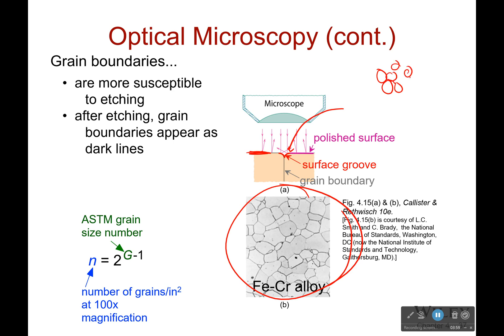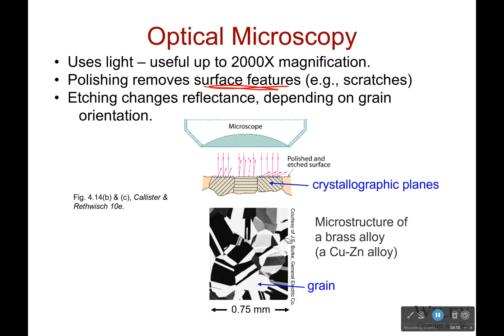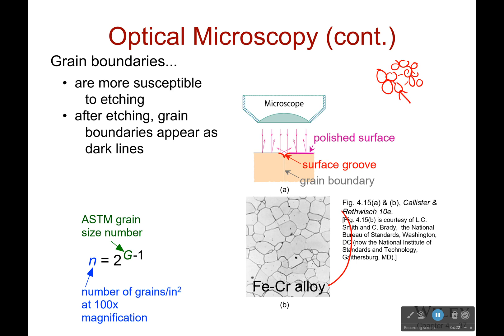Since the atoms at the grain boundaries are not bonded together very tightly — if at all — you're going to be able to knock out those atoms because they have less holding them down. Depending on how hard you etch, you'll either see a strong relief or, if you etch fairly lightly, it will just accentuate the grain boundaries. Either way, the grain boundaries are going to come into focus and you can examine them at a certain magnification.